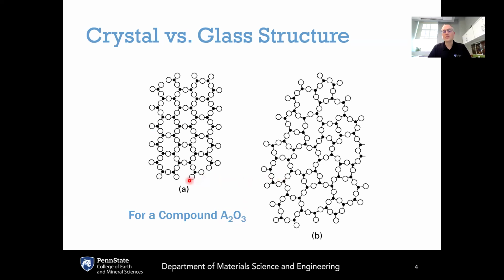Or in other words, both the crystal on the left and the glass on the right have the same basic structural unit, where there's this A cation, which is the smaller black circle in the middle. This is the cation A, and the cation is surrounded, in this case, by 3 of the oxygen anions. Those oxygen anions are represented by the open circles. So there's a coordination of 3 of these oxygens around each one of the cations A.